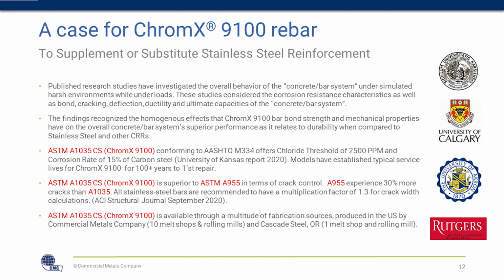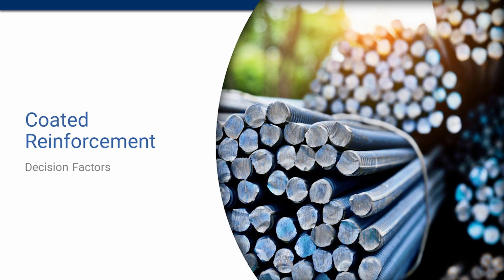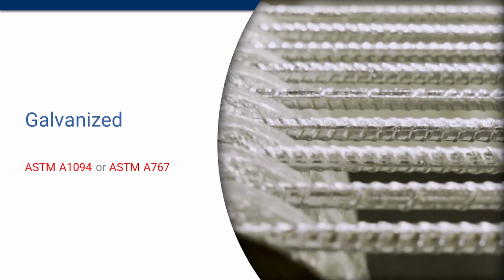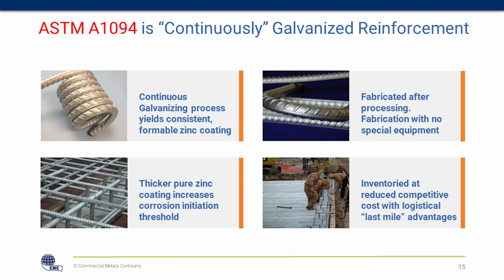And then as far as crack width or crack quantities, the A955 experiences 30% more cracks. And so by reducing the cracks, you're able to keep the concrete matrix and surface healthier. Getting into the coated materials, we'll start with galvanized, which has 2 standards. There's A1094 and 767. We'll start with the continuously galvanized reinforcement, which is produced with an automated process.